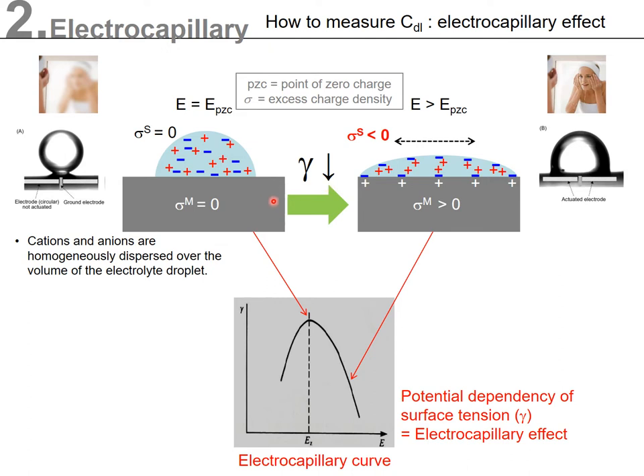Here, I have a metal plate or electrode, and then I have dropped a droplet of electrolyte. Let me say this electrolyte is the sodium chloride solution in water. So we would have sodium plus and chloride minus ions here and there. Also, I'd like to assume that this situation is at the point of zero charge, here, point of zero charge. It means we don't have any excess charges on the metal, and also there are no excess charges in the electrolyte, especially around the surface.